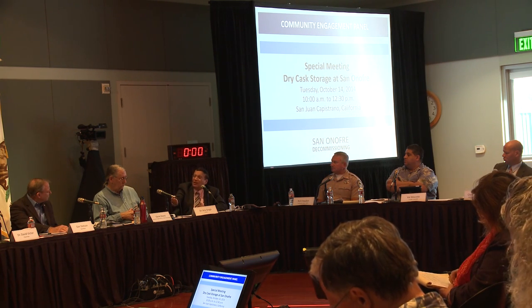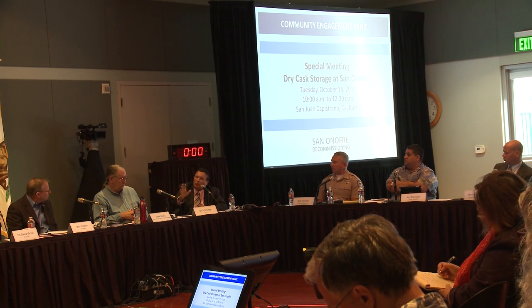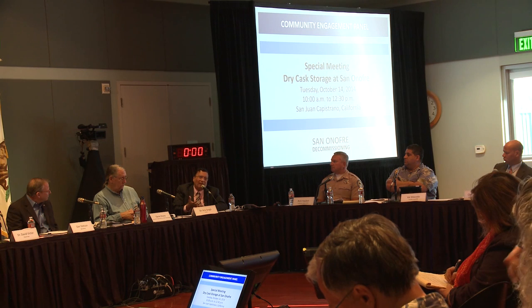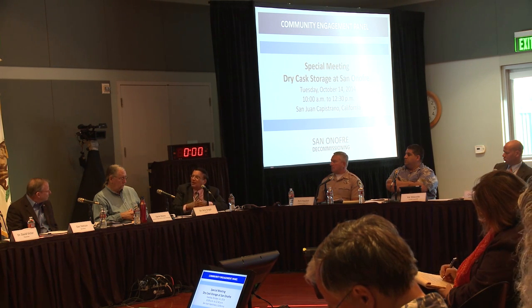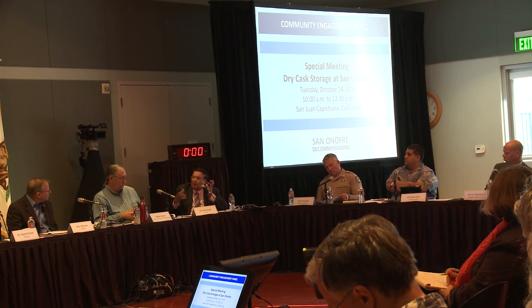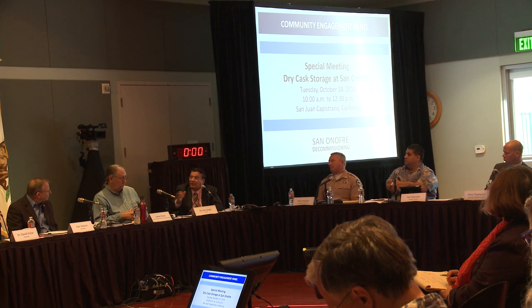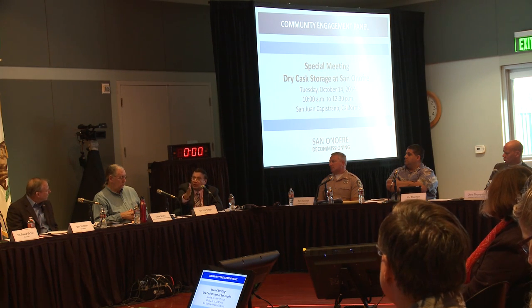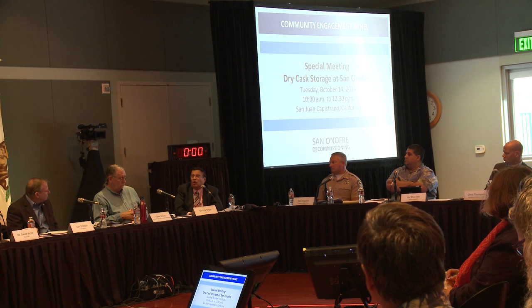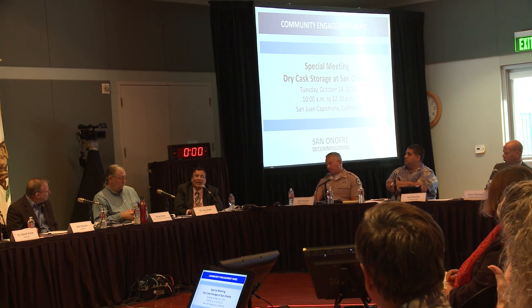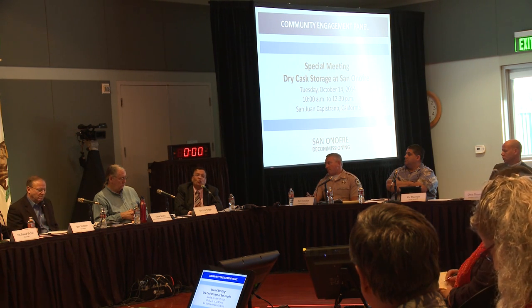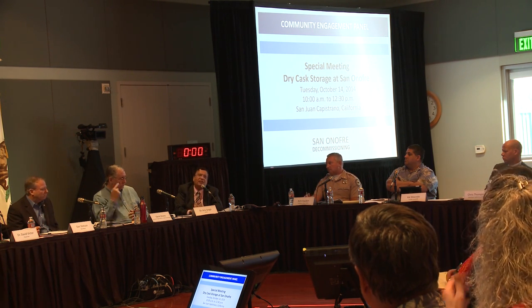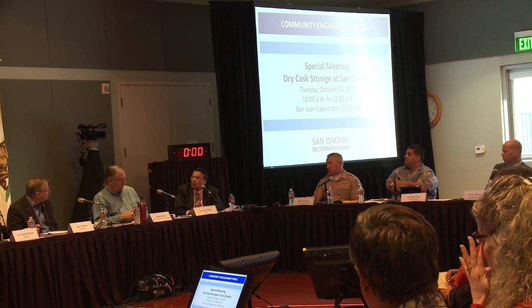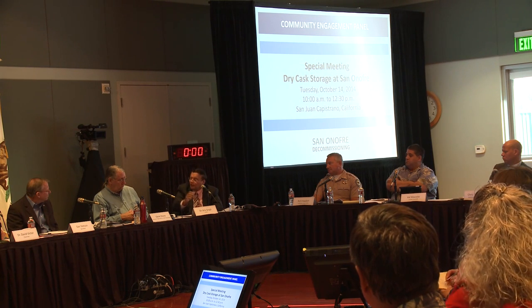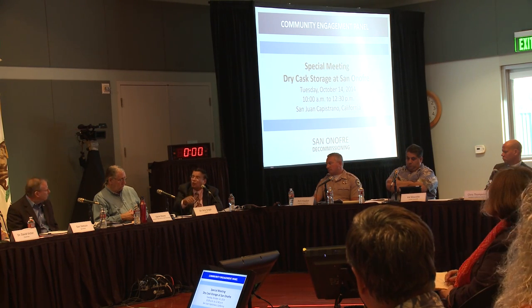Now, the way damage progresses is you will first, if you have salt attack, and salt is a bad word, I guess it's a common word. You have sulfates, you have nitrates, you have nitrites, you have chlorides, you have fluorides, of sodium, calcium, magnesium, you have a whole amalgam of things that constitute the deposit, and they attack differently. But the one thing is common, you're gonna have pitting first, and that pitting will then lead to intergranular corrosion. That's what the cross attack occurs. If you have pure chlorides, you end up getting stress corrosion cracking, which is transgranular attack. In either case, you will see surface indication, as Mike correctly said, before it will progress and you will have a through wall damage. So yes, doing the surface examination gives you plenty of time, and especially if you use the precursor coupons that I mentioned, then you'll know years before you'll have any damage.